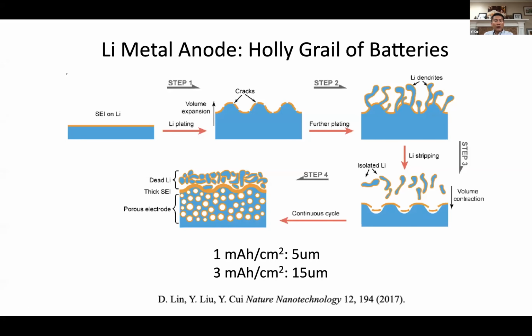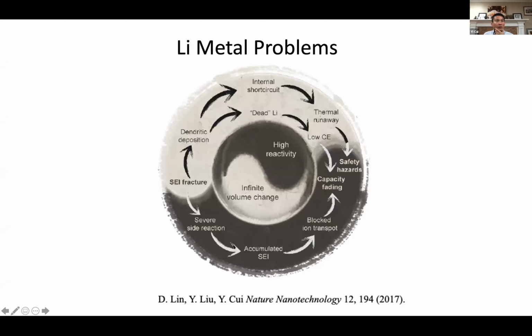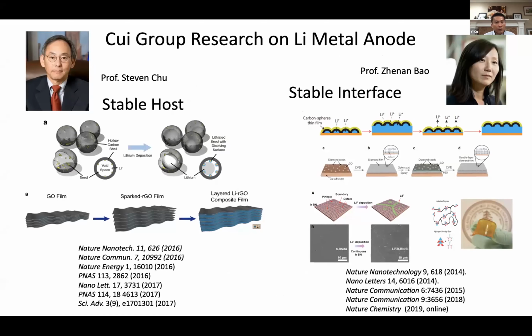This huge fluctuation, together with high chemical reactivity, are in our mind the two root causes we need to take care of. Many things are surrounding phenomena. And we need to design a strategy to solve this problem. At Stanford, in my group, I work together with Professor Steve Chu and Professor Zhenan Bao a lot, and also a few other faculty as well. So in 2016, we designed a concept and published for the first time a stable host. Just like graphite hosting lithium, silicon hosting lithium, now we have a metallic lithium host. And we published a number of papers to illustrate this concept.